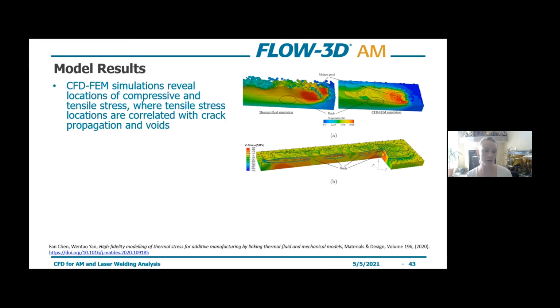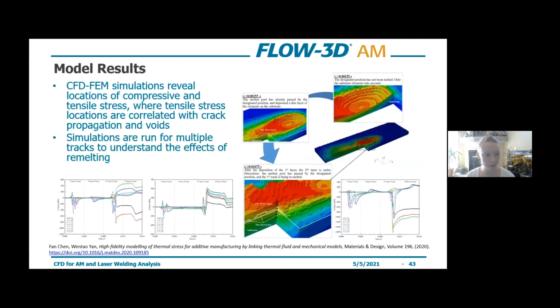So you can see from the results here, by plotting tensile and compressive stress, that where voids are forming, we're getting higher tensile stress values. So that's a good indication: if you're seeing high tensile stress in your FEA simulations, then you can reasonably assume that's going to be the location that cracks will form, if they do.